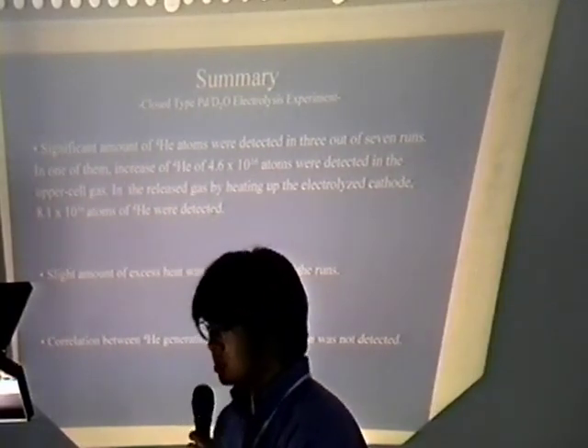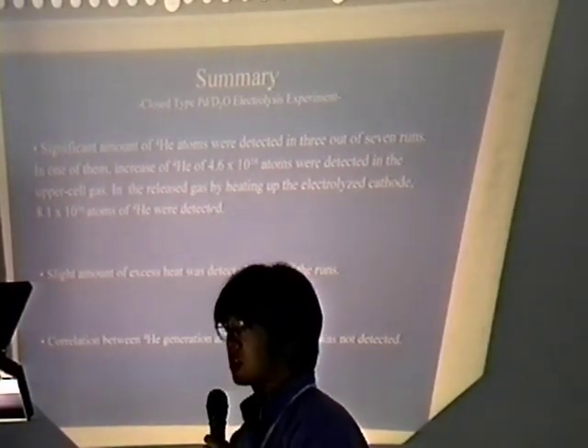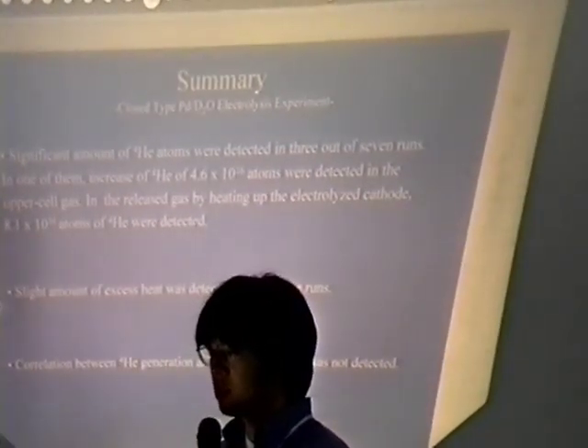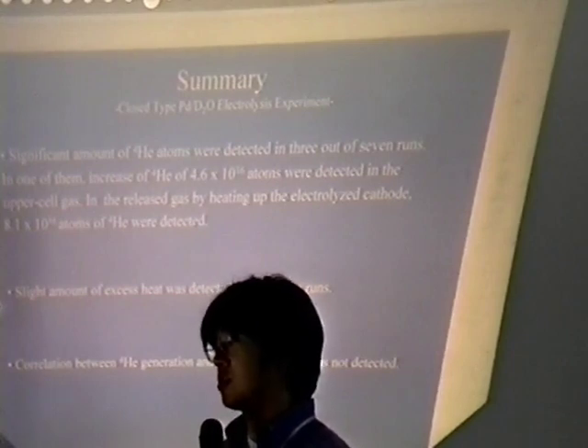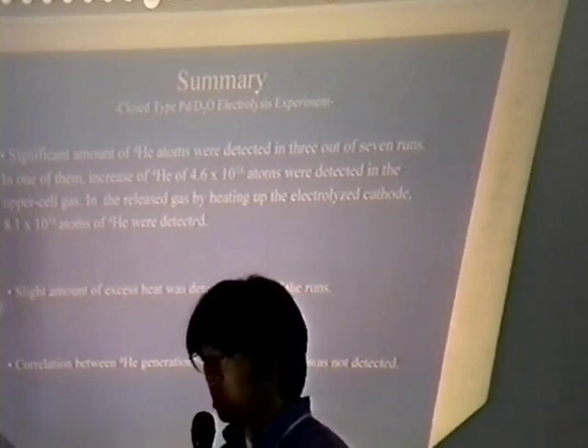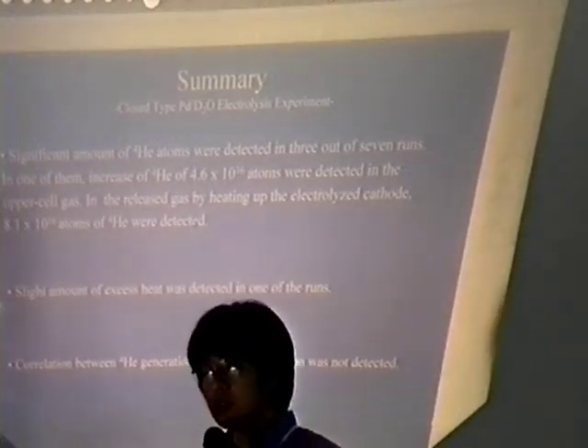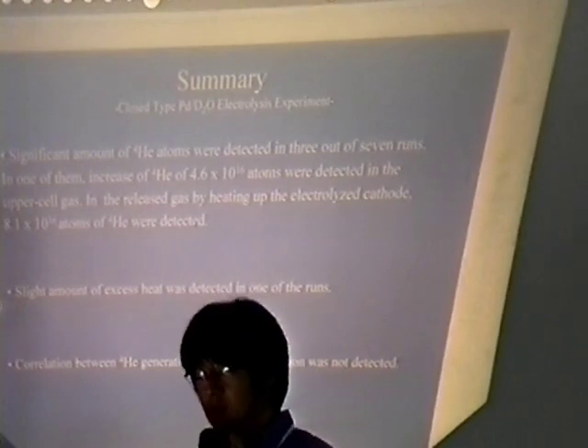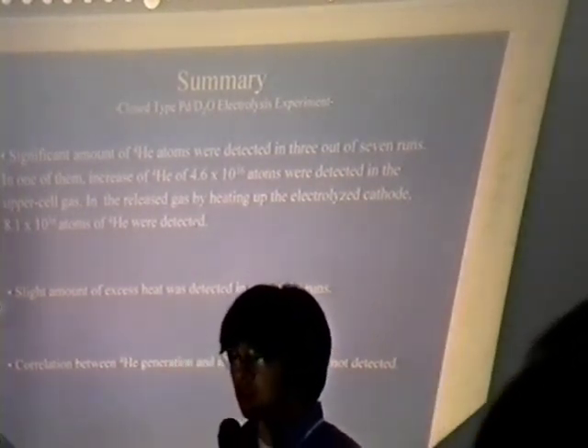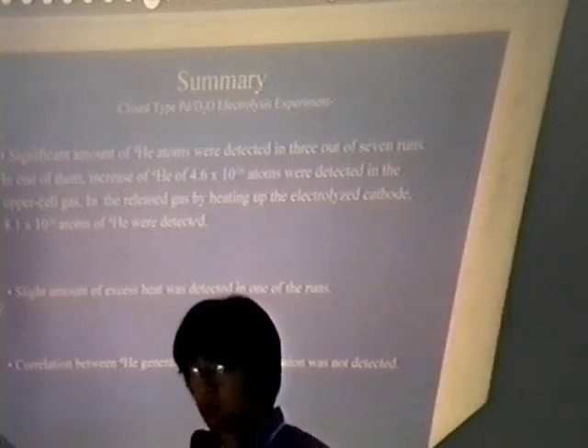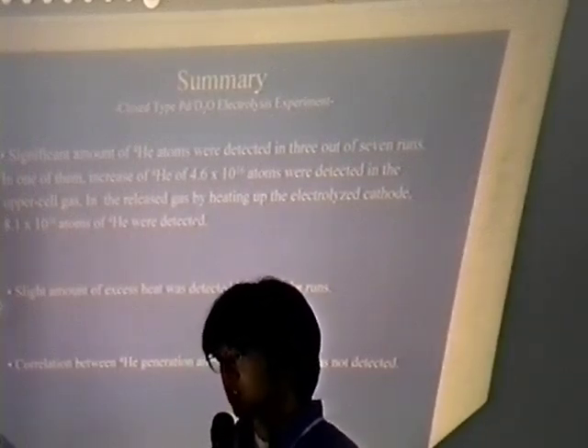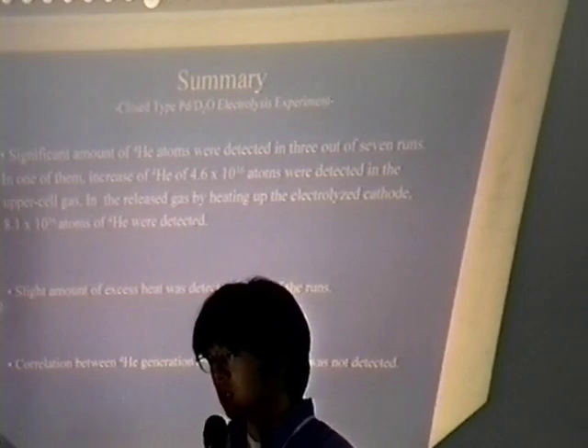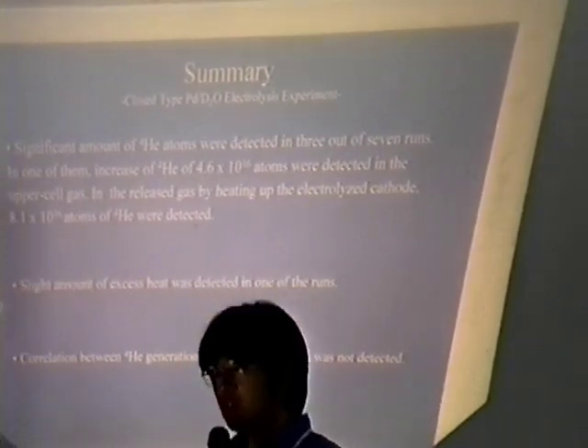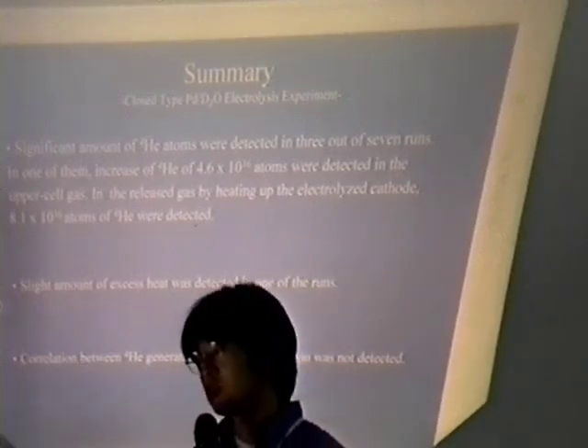This is a short summary of this experiment. A significant amount of helium-4 atoms were detected in 3 out of 7 runs. In one of them, an increase of 4.6 times 10 to the 16th atoms of helium-4 was detected in the upper cell gas. In the gas released by heating up the electrolyzed cathode, 8.1 times 10 to the 16th atoms of helium-4 were detected. A slight amount of excess heat was detected in one of the runs. Correlation between helium-4 generation and neutron emission was not detected.